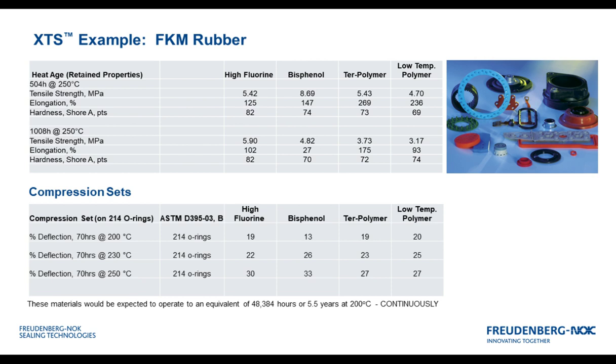Here are results of some extreme temperature testing. These fluorocarbon-based compounds offer exceptional chemical resistance as well as sealability. You can see here compression sets that have been done on O-rings. O-rings were chosen because it's the most severe. After exposure to 250 C, almost 500 degrees Fahrenheit, the values are less than 30 for the special low-temperature polymer.